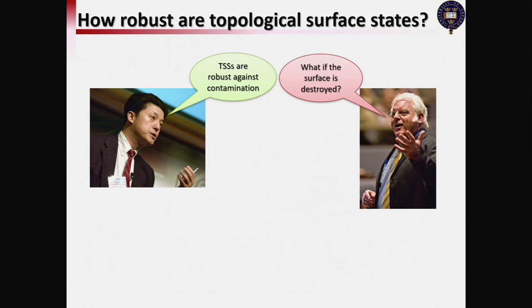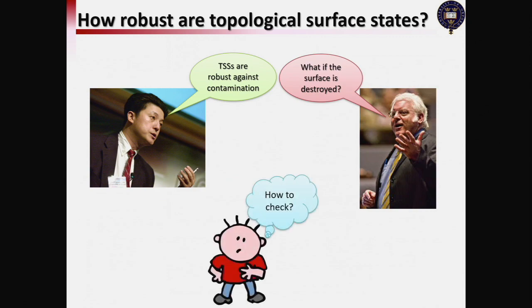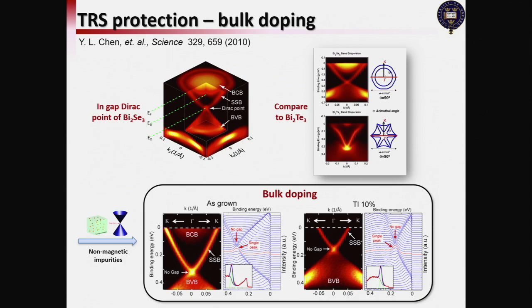And then as a surface scientist, I had the same question. What if I oxidize the surface? Shouldn't the surface state just disappear? So I was thinking how to check experimentally, and then we put that into practice. First, we tried to screw up, dope the system. The first thing we did was ask Jimmy Analytis to dope impurities into the bulk. That's not exactly screwing up the surface, but we introduce a lot of dirt in the bulk, and that will also have dirt on the surface.